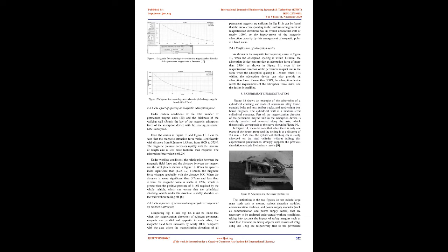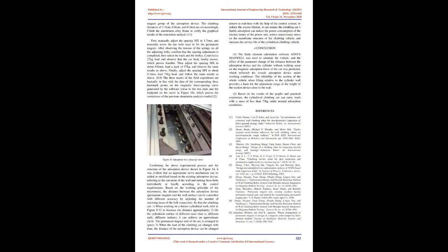2.4.2 The influence of permanent magnet pole arrangement on magnetic attraction. Comparing Fig 11 and Fig 12, it can be found that when the magnetization directions of adjacent permanent magnets are parallel and opposite to each other, the magnetic field force increases by nearly 100 N compared with the case where the magnetization directions of all permanent magnets are uniform. In Fig 11, it can be found that the curve corresponding to the uniform arrangement of magnetization directions has an overall downward shift of nearly 100 N, so the improvement of the magnetic adsorption capacity by this arrangement of magnetic poles is a fixed value.